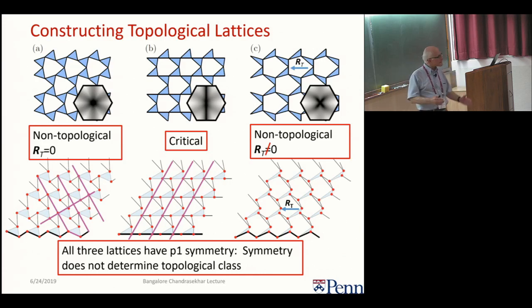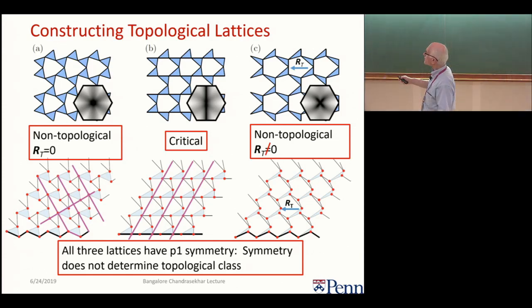The Kagome lattice itself has these 3 grids, and that complicates things. So he said, let's consider a lattice that has 1 grid, like this. So now I have only states of self-stress associated with these horizontal things, and just a single line of 0 modes in the Brillouin zone. Then what he does is say, if I take this point and move it down, and that point and move it up, rotating things, then I go towards the twisted Kagome lattice, which we had before, and it is gapped everywhere, as you can see from this. Or I can do it the other way. I can move this one up and that one down, and I get this structure.